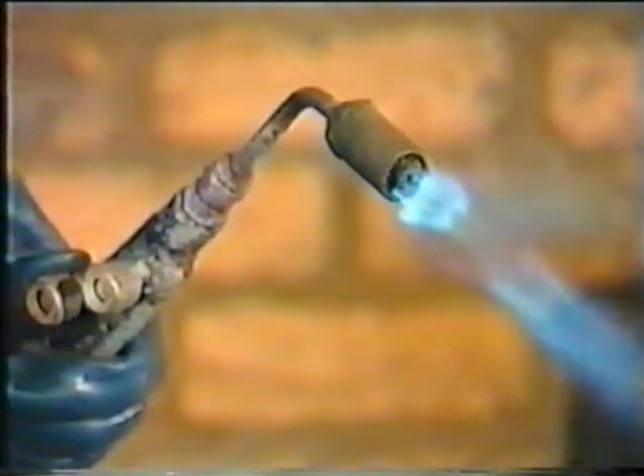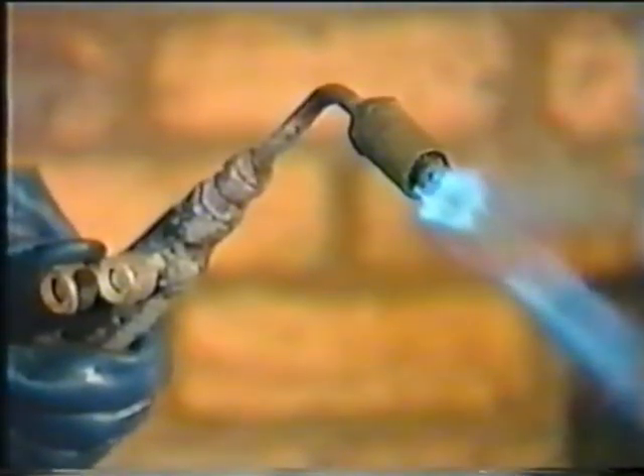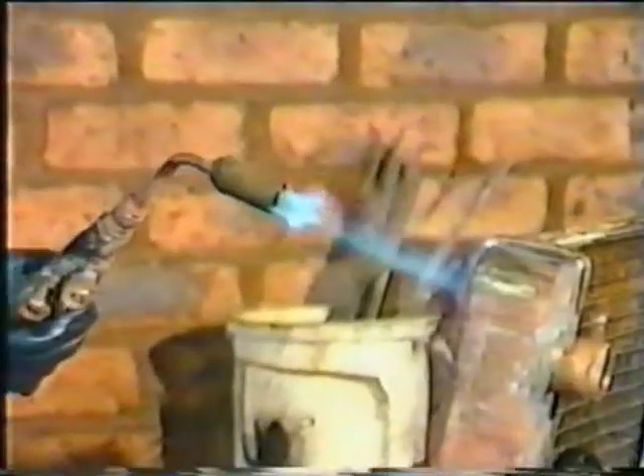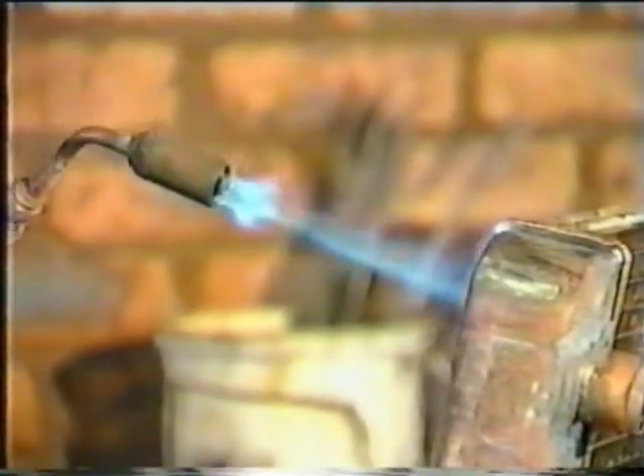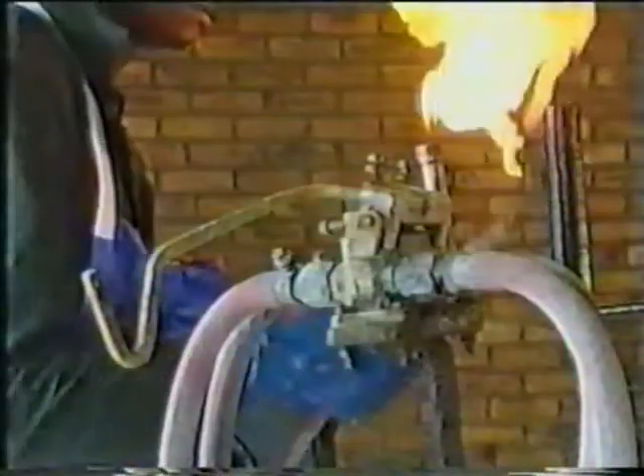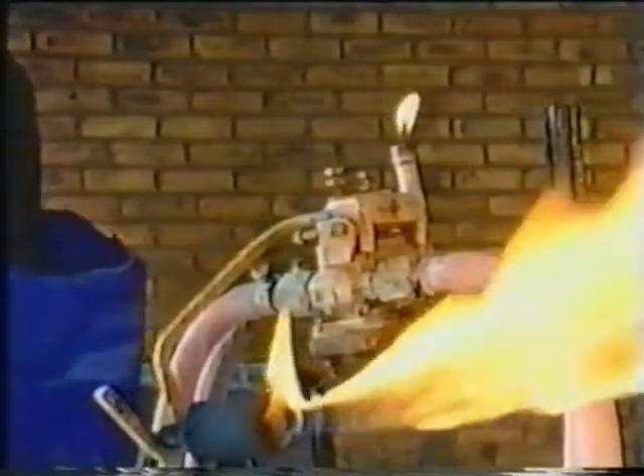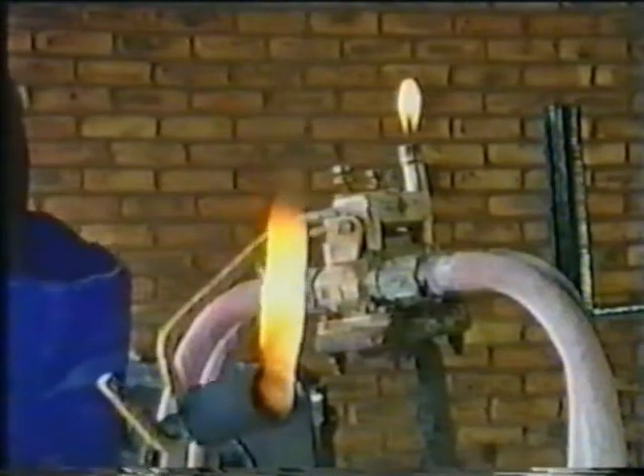A large torch flame causes overheating and damage, resulting in tube-to-header plate leaks. If the core is to be reused, it will be necessary to re-sweat the header plate. The only time you may need a broader spread flame is for stripping down old radiators. This is a flame economizer, a device which cuts off the gas when the torch is not being used.